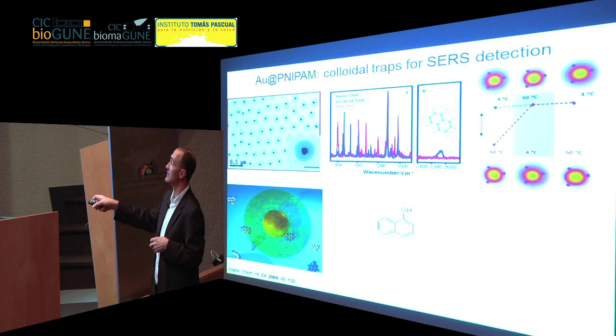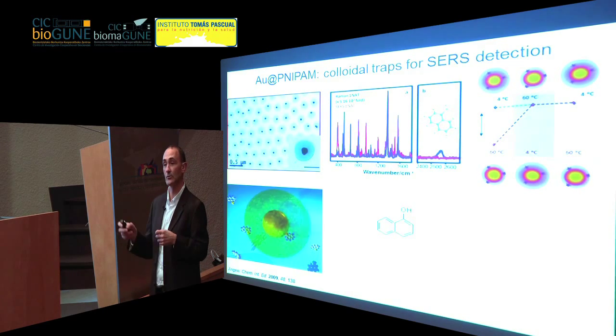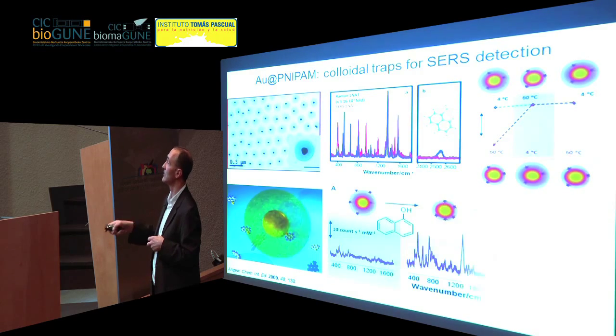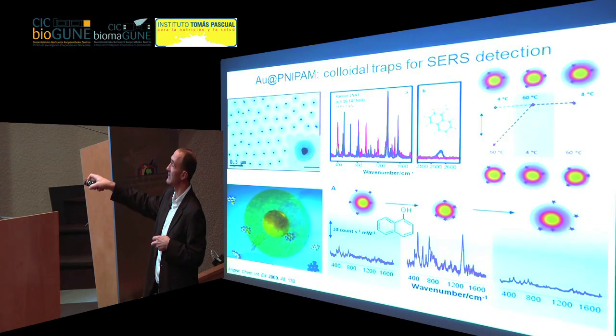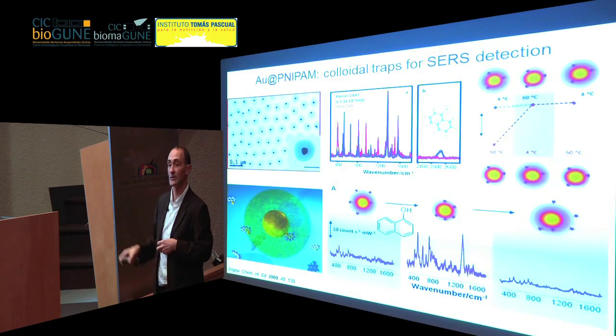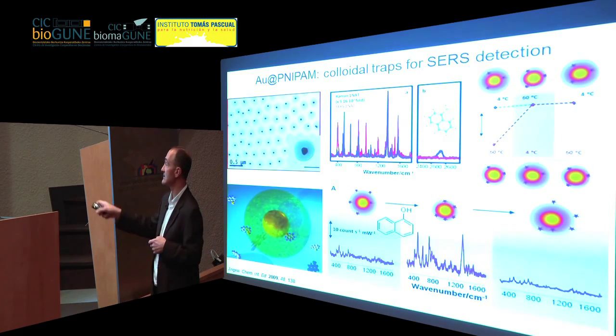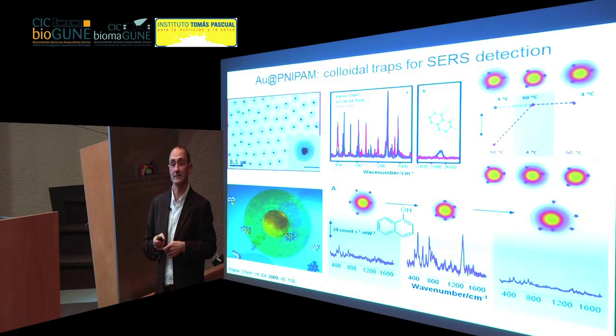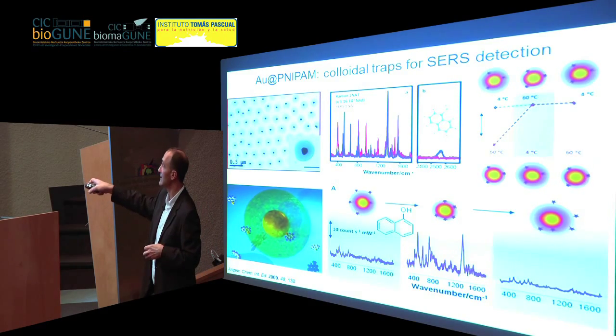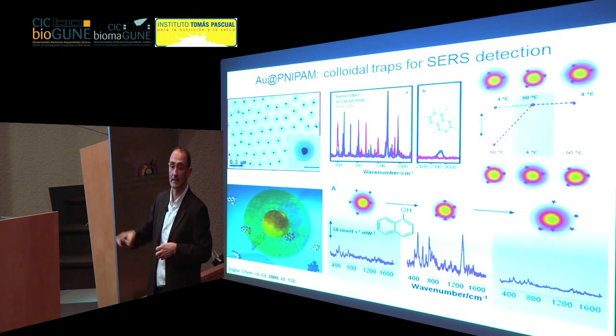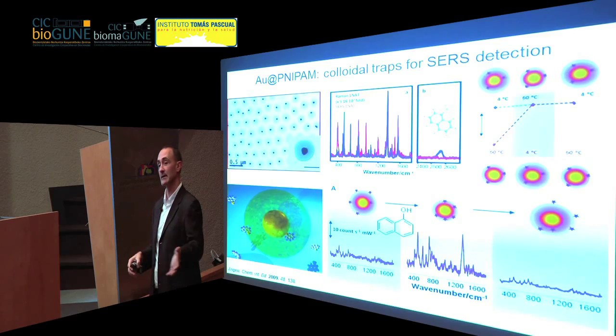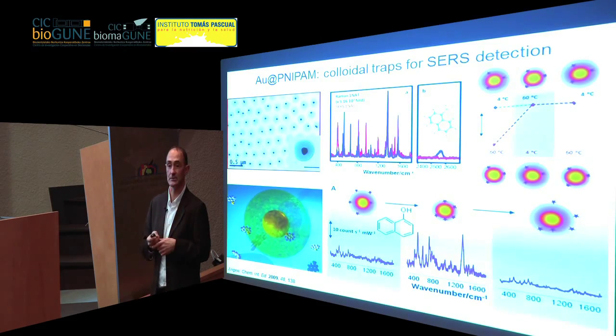The nice thing was that when we used a molecule that did not contain any functional group that could attach to the metallic surface, what we saw was this. So at low temperature, we don't get any nice signal because the molecules are diffusing in, but they can also diffuse out. There is no reason for them to stay close enough to the metallic surface. If we increase the temperature, then the shell collapses and it traps the molecules close to the core, and then we get this increase in the signal, fully identification of naphthol. This is the first ever published SERS spectrum of naphthol. And then if you lower the temperature again, the molecules diffuse out and you lose the signal again. So you can not only trap and identify the molecule, it's actually a reversible sensor.